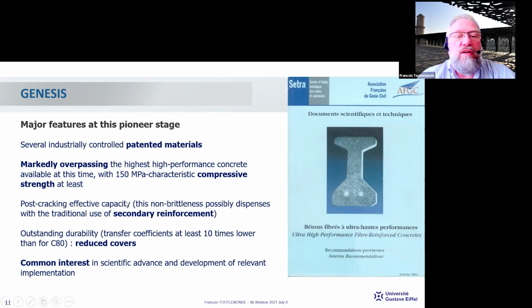Of course, the post-cracking effective capacity possibly dispenses with the traditional use of secondary reinforcement. And because of the outstanding durability, with transfer coefficients at least 10 times lower than for C80, it was anticipated that reduced covers could be used. And what's important for the future of this material, it was recognized that there was a common interest of all the stakeholders in scientific advance and development of relevant implementation.